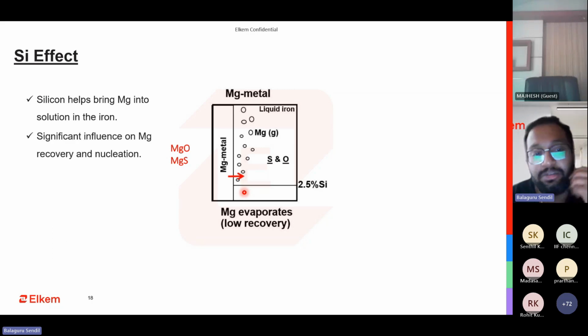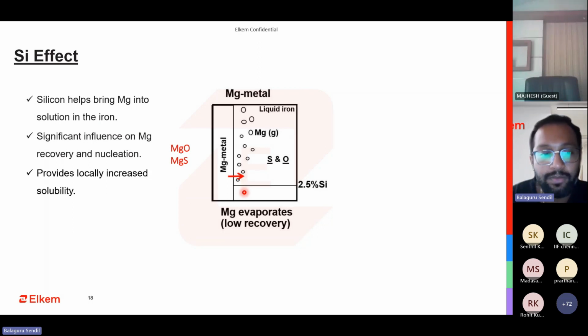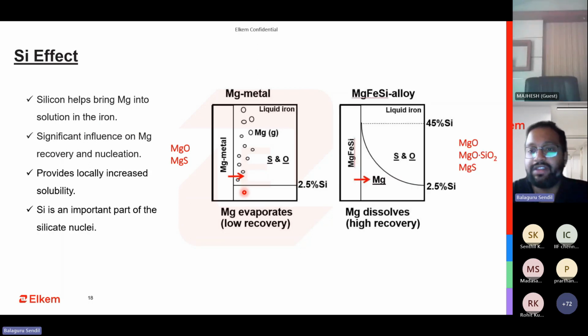Significant influence on magnesium recovery and nucleation. This is the dissolution curve for a ferrosilicon magnesium alloy. You see the curve is like this. So it actually improves the tendency of the magnesium to dissolve into your system, so that more of the nucleating sites, MgS, are created instead of the magnesium just going out and burning as slag. So silicon is an important part of your silicate nuclei. We saw the shell: the core is MgS and it is surrounded by a complex silicate shell. So it again influences the amount of silicon that you have.